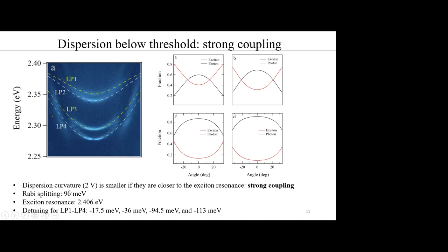The Rabi splitting we obtain is around 90 meV, and the detuning for the lower branch polaritons LP1 to LP4 are listed here. The Hopfield coefficients for these polariton branches are plotted here. We can see that the cavity photon component increases from LP1 to LP4, which is consistent with the curvature of these polariton modes.